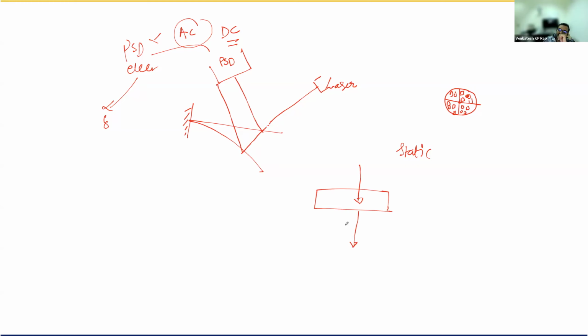If I want to make it reflective, then I have to coat it with either gold or some other reflective material on top of it, right? Then it indeed will change the properties of the material completely. So rather than a simple structure, like how I showed you for a simple cantilever, it now becomes a composite beam. Again, this also becomes a composite beam, right?